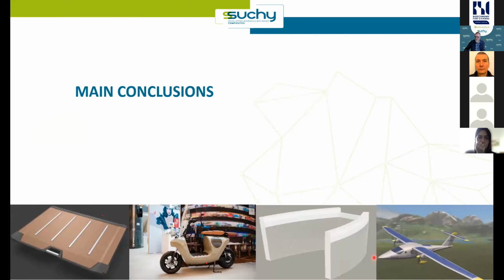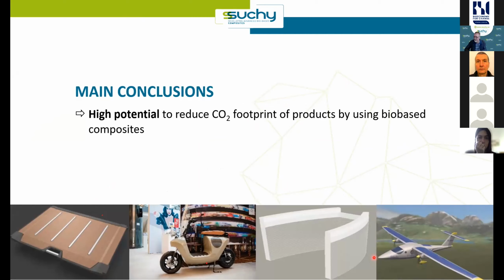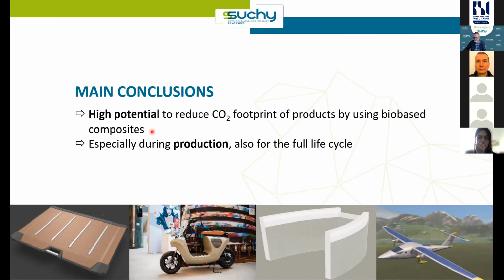So to conclude this short presentation, I think that we can say that, resulting from the very extensive analysis that we did, and I only showed the final results here, we can conclude that there is indeed a high potential to reduce the CO2 footprint, which we hoped for, of course, at the start of this project, and which is not evident, I have to say, for bio-based materials. But there is indeed, for the solutions developed in this project, a high potential to reduce up to 2 times the CO2 footprint in the production phase. So especially during the production phase, there is a reduction.